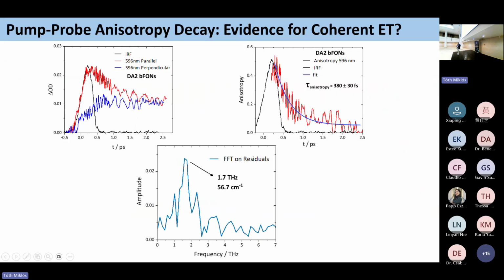Then recently, we also started to apply pump-probe anisotropy to these systems. Here I have some very preliminary data that I show for DA2 bFONs that were collected at 596 nanometers. From this data, we can see the anisotropy track for the system, starting from a value of 0.4, shows an ultra-fast decay that has been fitted with a lifetime of 380 femtoseconds. So it is a lifetime very close to the lifetime that we have assigned to the energy transfer in the case of the magic angle femtosecond transient absorption experiment.